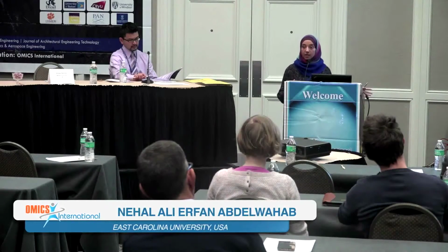In this process, a combustion happens to the fine iron ore particles and secondary iron oxide wastes in the presence of lime and coke to produce a molten mass. This molten mass is solidified after that into porous pieces, which are crushed to smaller particle sizes. Those particle sizes are divided into three categories. The particle sizes larger than 20 millimeters are supposed to be a burden to the blast furnace, from 5 to 20 millimeters can be reintroduced in the sintering machine, and less than 5 millimeters are considered a waste.